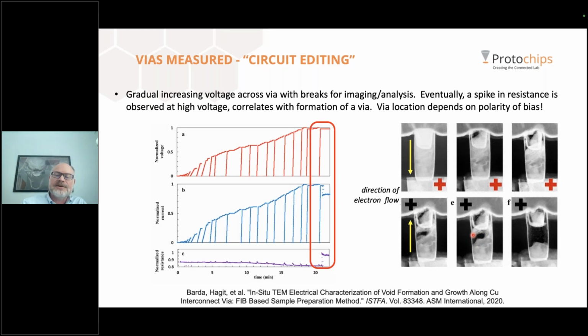Now, once the via structure is isolated, you can start to do in situ imaging and analysis. So here on the left, you can see the voltage was slowly increased while monitoring the current and resistance of this via. Now, the breaks you see here, these vertical lines, are times when the biasing was paused to allow closer inspection in the microscope. But what you see over time is that as voltage is increased, you do see a spike in resistance at a very specific voltage.